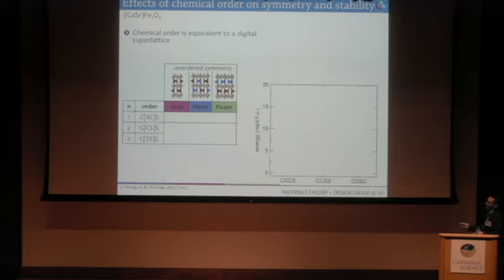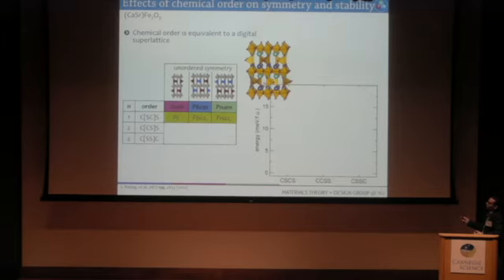And there are three possible orders. The first one I'm going to show you here is where we have alternating strontium and calcium in every other layer. In analogy to perovskite superlattices, this would be a 1-1 period brownmillerite superlattice. Again, the effect of adding the chemical order on the symmetries induced by the tilt or by the tetrahedra and octahedra is to reduce the symmetries to all polar space groups. And what I put in brackets here, the S and the C, corresponds to strontium and calcium here, bridging the octahedral unit like that. So this is a 1-1 period superlattice.